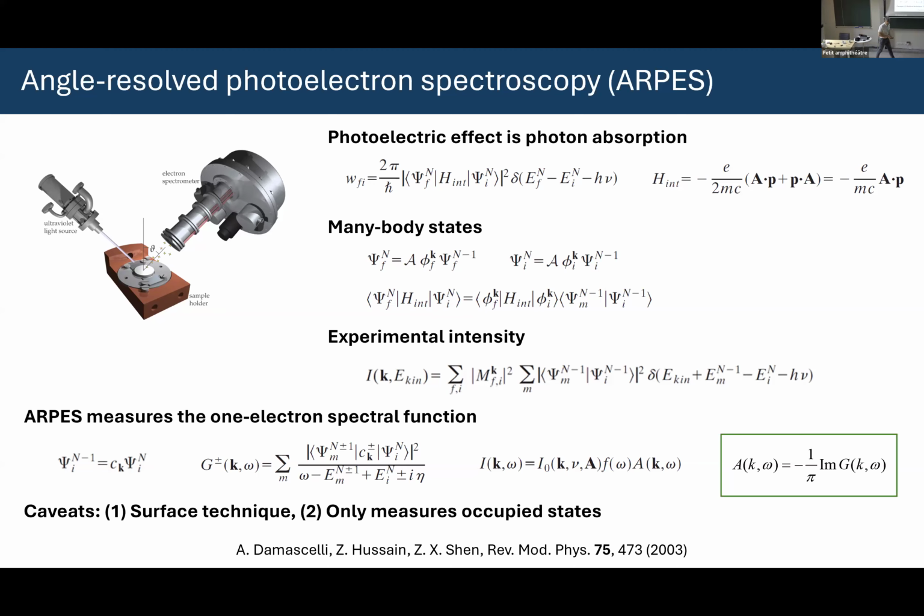Well, okay, time resolved. What they do is they hit it with a laser, and then you excite a bunch of electrons above the Fermi energy. And now there's some holes, and then you see some stuff. And what that stuff is, is the unoccupied states in the presence of a bunch of now holes in the occupied states that are interacting with them. So if interactions are completely irrelevant, you can see some vestiges of the unoccupied band structure. So usually the effective masses are wrong because they're renormalized by interaction with all these holes. It's a way to get a little glimpse of what's going on.